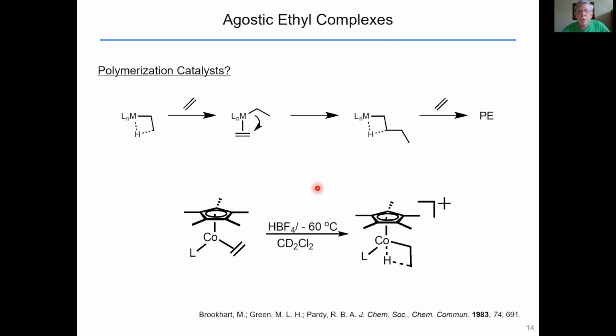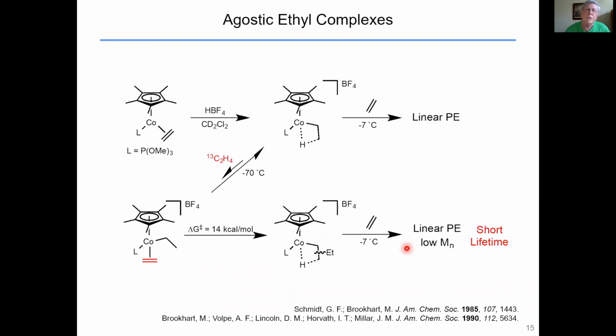So the system we're going to test is exactly the cobalt system that I showed you on the previous slide. We take this cobalt ethylene species, protonate it, and generate an agostic species. And in fact, if you expose this agostic species to ethylene, you grow a polyethylene chain. We were able to actually observe the ethyl ethylene species using C13 labeled ethylene and see the barrier to migration. It's about 14 kilocalories per mole. And then we can actually just watch the chain grow. We get linear polyethylene, but it's a low molecular weight and it has a fairly short lifetime.